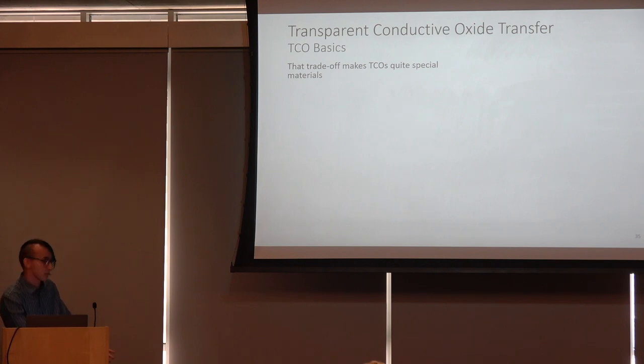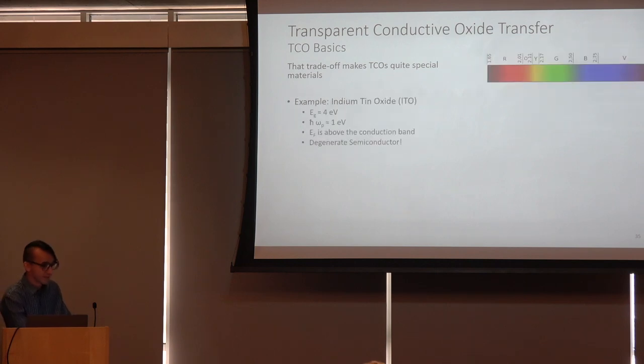This brings us to transparent conductive oxides. These materials are quite special. An example of such material would be indium tin oxide, which is a semiconductor, a degenerate semiconductor, but a semiconductor nonetheless. And it has a band gap of about 4 electron volts, which is slightly into the UV. And then the photon energy corresponding to the plasma frequency is right around 1 electron volt, slightly into the IR. And so it has this transparency window that very neatly nests the visible spectrum. It makes it exceptionally useful for all sorts of optoelectronic devices. Your cell phone screens pretty much all have ITO.